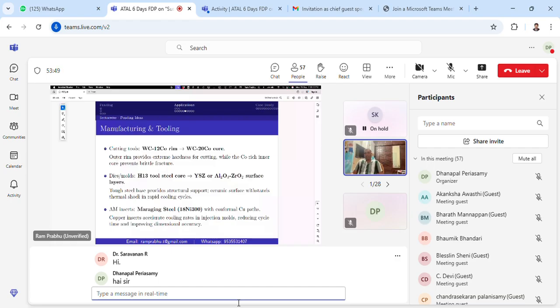Similarly, in the dies, H13 tool steel, which is a very famous tool steel, is used to make the dies or molds for sand casting, investment casting, pressure die casting, or the forging dies or extrusion dies. If you coat that with ceramic like yttria stabilized zirconia, aluminum oxide, or zirconium oxide, this helps to provide thermal shock resistance, because you have rapid heating and cooling cycles in the dies, either in the forging or the casting process. So it needs a high thermal shock resistance, which can be offered by these ceramic coatings.